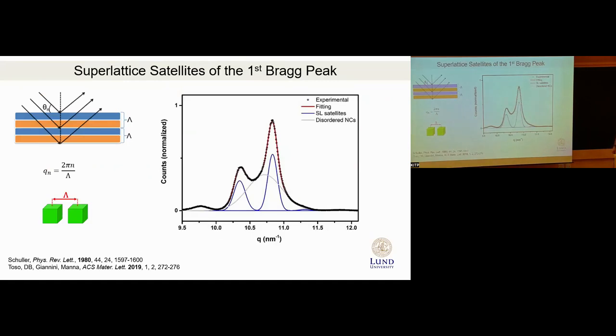The origin of this peak splitting arises from what's called the multilayer diffraction effect, which was first observed by Schuller, in bimetallic superlattices grown by metal evaporation. It has been observed in the 80s. When you have alternating layers of two materials with different electron densities, you have a secondary interference effect. And this is what we see in these perovskite superlattices. So you can just apply Bragg's law. Another way to look at it is that it works as a diffraction grating, and you see different orders of diffraction due to the superlattice.